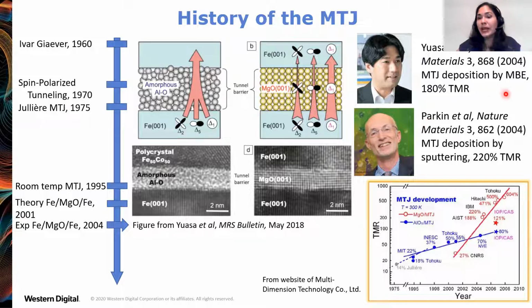This was done by Shinji Yuasa and colleagues, showing TMR of 180%, and Stuart Parkin and colleagues showing TMR of 220% with MgO tunnel barriers. And as the work progressed to try to get higher and higher TMR, now you can see upwards of 600% with MgO tunnel barriers at room temperature, whereas the best values you can get with amorphous aluminum oxide tunnel barriers is around 80%.